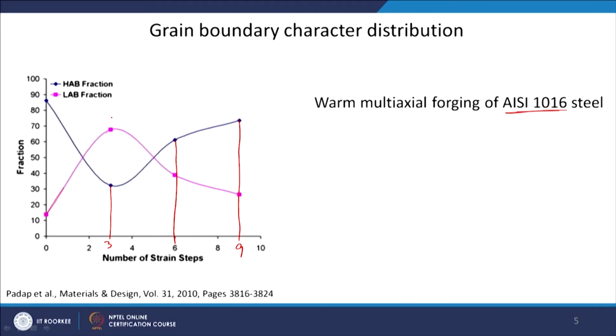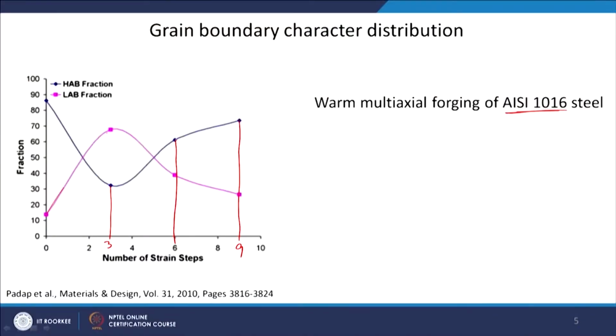So, this initial phase is the development of the substructure, grain subdivision by having low angle grain boundaries within the grain. If you keep deforming, now after 6 pass you can see that the high angle grain boundary fraction is again increasing from 30% to around 60%, and with further deformation it is increasing up to 70%. So, with the grain refinement, initially the grain is divided into subgrains, and now these subgrain boundaries are converting into high angle grain boundaries. So, after 9 pass, for example, you will have a refined or ultrafine grain material with a very small grain size, and most of the grain boundaries are high angle grain boundaries. So, this is a typical grain boundary character distribution as a function of strain or as a function of passes during any SPD process generally.